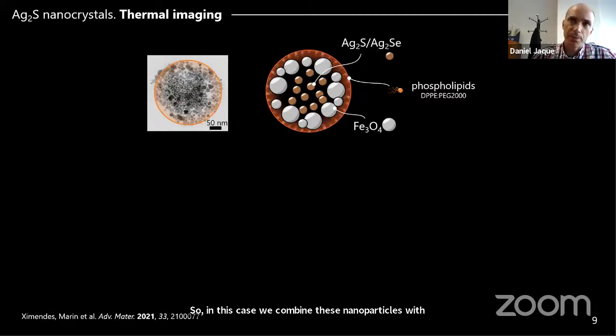And you know that magnetic nanoparticles are nanoparticles that can generate heat if they are inside an alternating magnetic field. So the idea is to monitor the temperature of the magnetic nanoparticles by using the luminescence of silver sulfide nanoparticles that, as I told you, produce emission spectra that is strongly dependent on temperature.